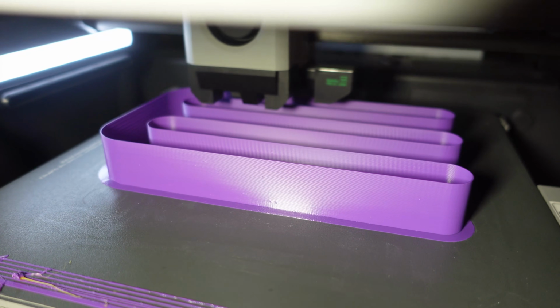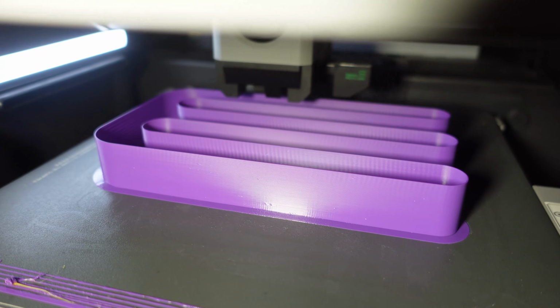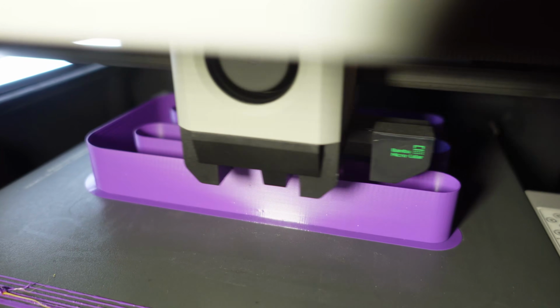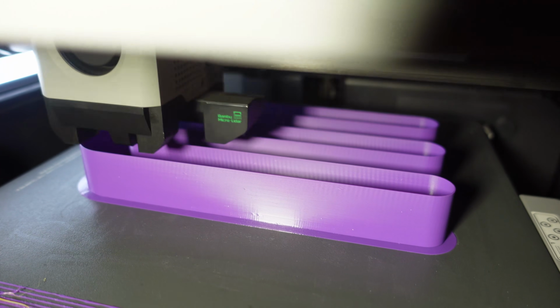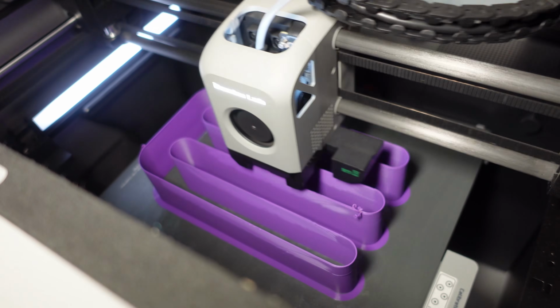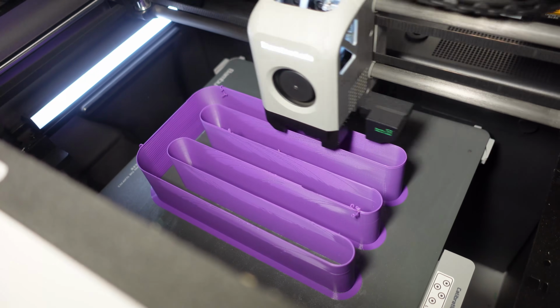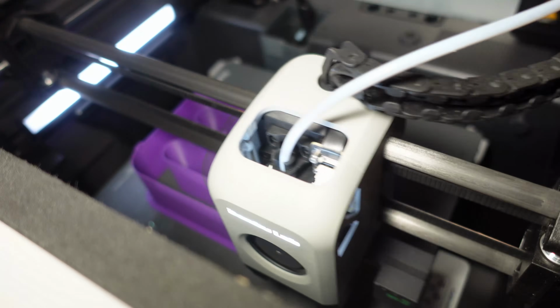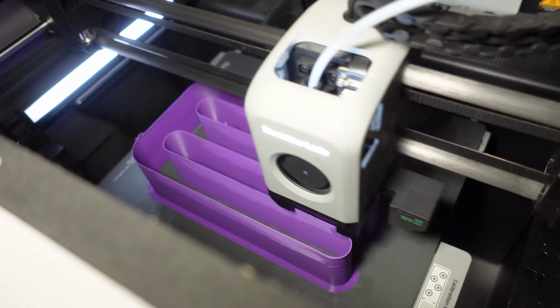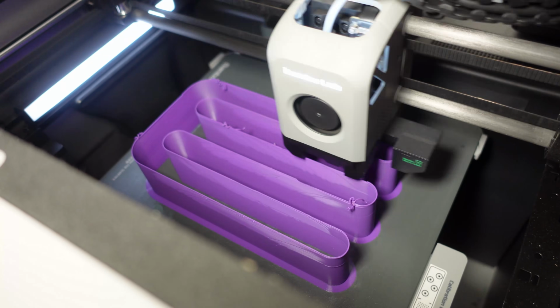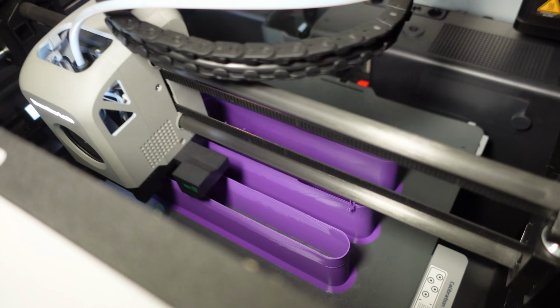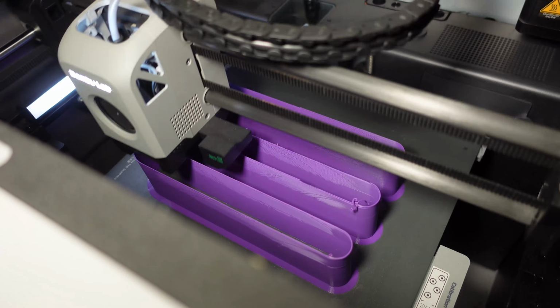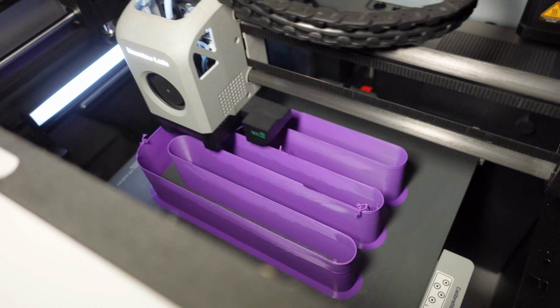PETG 67% and looks like PLA so far. Print temperature 265 degrees Celsius. Printing at 85%. Two PLA printings were stopped far before this. Of course I can see some under extrusion even here, but I will leave it so far. I can hear quite big clicking of the extruder. Probably I have to stop it soon.